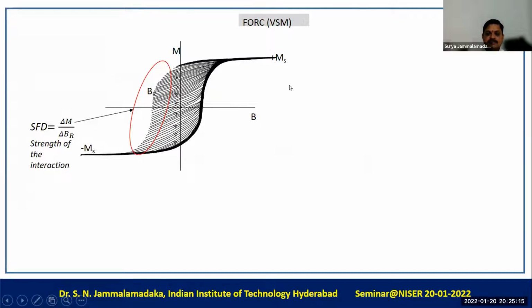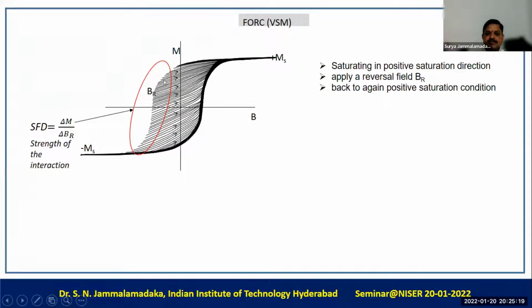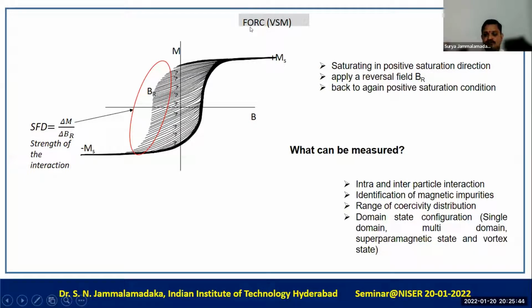The first order reversal curves can basically be obtained by saturating the magnetization loop up to positive saturation, then applying a reversal field, then going back to positive saturation. If you repeat this several times, you get the first order reversal curves like this. The importance of FORC is that one can get information about intra and interparticle interactions, identification of magnetic impurities, the range of coercivity distribution, how the coercivity is distributed within the sample, and domain state configuration. You can say whether you have a single domain, multi-domain, superparamagnetic state or the vortex state. All this information can be obtained from the first order reversal curves.